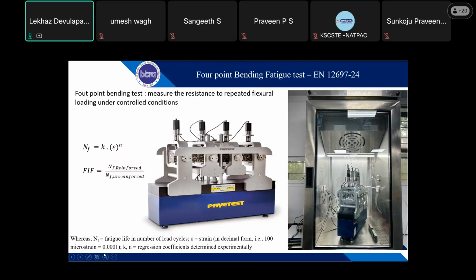We can do this at our chosen temperatures. Here we have a temperature cabinet, so the whole testing can be done at a specified temperature. We did this test at 20 degrees. The test instrument is placed in a temperature chamber, and we record the number of cycles to failure, and then we calculate the NF, or the fatigue life of the pavement, based upon the strain we have applied and the regression constants we get from the graph.